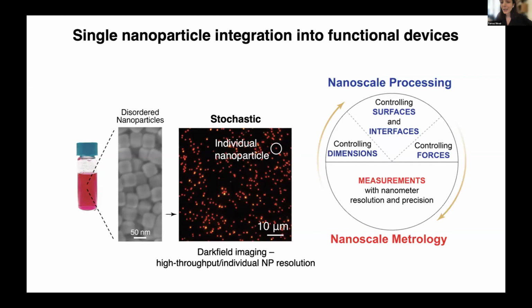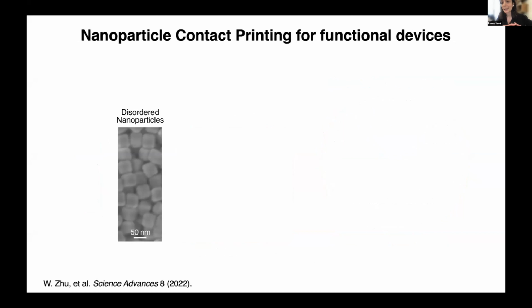Another point to keep in mind, as the nanoparticles get incorporated into the device, which is either electrically, optically, mechanically, or through other means active, the properties of the nanoparticle are now going to start being influenced by the complex environment surrounding it. So oftentimes conventional techniques, SEM, TEM, AFM wouldn't be sufficient for studying the nanoparticle in a device format. So other techniques would be necessary.